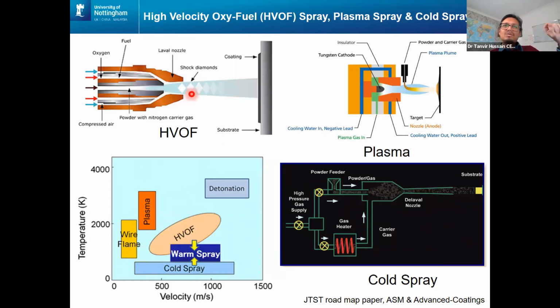So if someone looks into the HVOF flame, they would be able to see the shock diamonds coming in. And in that supersonic flame, we inject powder or suspension. These particles accelerate, get molten, hit the substrate, and develop a coating. So HVOF tends to be velocity-wise traveling between 500 to thousands of meters per second, much faster, but temperature-wise much cooler than plasma. And at the other end of the technology, we have got something called cold spray.